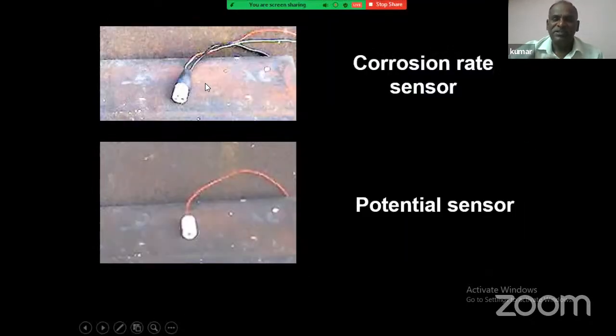At CSIR, we have made two kinds of sensors. Number one is a corrosion rate sensor, a 3-electrode system, and another one is a potential sensor. This one is made of MnO2 solid electrolyte, and it can be used as a reference electrode. This can be used as a corrosion rate sensor. Whatever was done in the previous one, the same work we can do with this, and with certain hardware, we can find the corrosion rate at any instant when it is embedded inside the concrete.